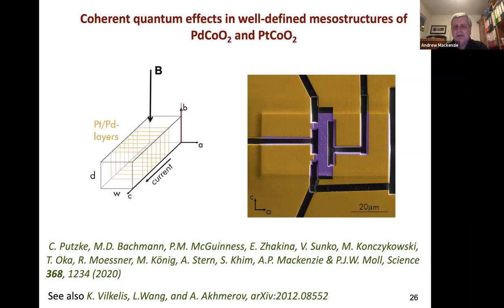And you know, the out of plane resistivity is uncertain within a factor of 5, because that will be the spread of estimates that different groups are giving you. So Maya and Philip and Carsten Putzke had the idea that a rather neat way to investigate that would be to make special devices, where what we're looking at in this purple false colored picture of palladium cobaltate is that the C-axis is running along the bar now. So it's a series of AB planes with the C-axis going this way.